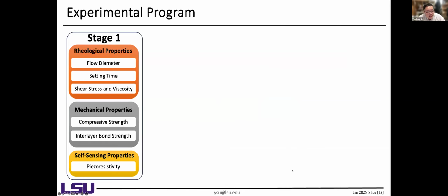So we start from the first stage. In the first stage, we start by measuring the rheological properties, including the flow diameter, setting time, shear stress and the viscosity, because that is important for 3D printing. We also test the mechanical properties, including the compressive strength and the interlayer bonding strength. The compressive strength, of course, is really important for infrastructure, and the interlayer bonding strength matters because we are thinking of it as a permanent formwork. So we're going to have the formwork, and then we cast the concrete. This bonding is really important and essential to make sure of the integrity of the structure. Later, we test the self-sensing properties of those materials.